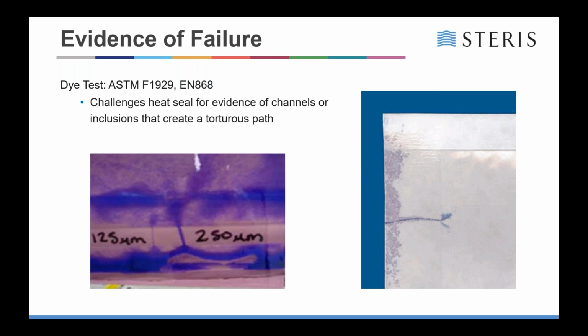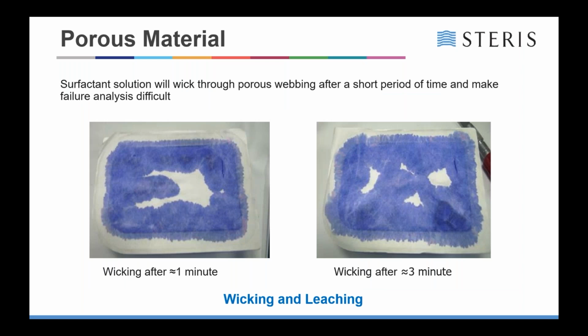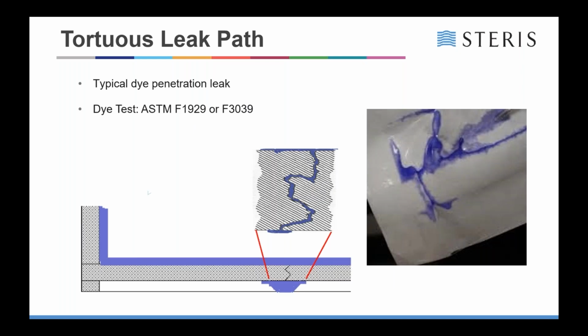The picture on the right-hand side is an actual defect that was found in a customer's pouch, and you can see how very clear that is. The problem, as I said, is the wicking and leaching of the dye through the materials. The tray shown in both pictures here was approximately A4 size. So you put 5 milliliters of dye along the seal and run it around each of the seals, and you can see where it is after 1 minute and after 3 minutes. Any defect that was in there will disappear in a very short period of time.